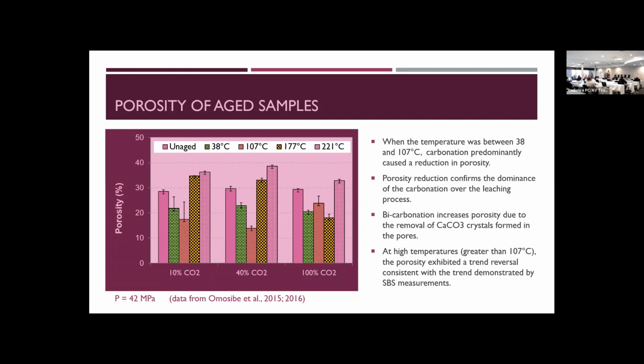CO2. Probably it is because the porosity reduction confirms the dominance of carbonation over the leaching process, but bicarbonation increases the porosity due to the removal of calcium CO3 crystals forming the pores. We believe the effects here probably need a little more detailed information, but it is a clear effect of the CO2 on the performance of our samples.